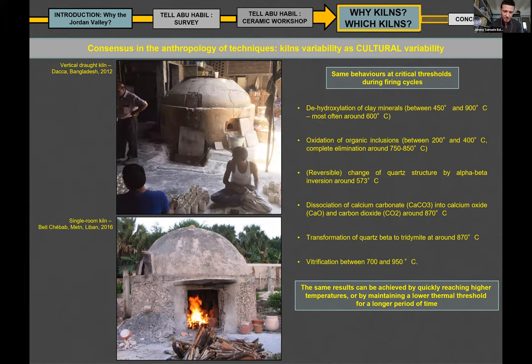All these physicochemical transformations happen around very specific thermal thresholds. The way this transformation happens, the ability of the different types of kilns to make these transformations occur, is what we call performance. And therefore, it's quite surprising to observe that for all these very significant physicochemical transformations during the firing cycles, experimental and ethnographic data agree on the fact that it is possible to reach temperatures above these thresholds quickly, or to keep the vessels for a few minutes longer around a lower thermal threshold for this transformation to take place. They take place anyway, either if we exceed certain temperature thresholds very quickly, or if we maintain a lower temperature, but for a longer period of time.